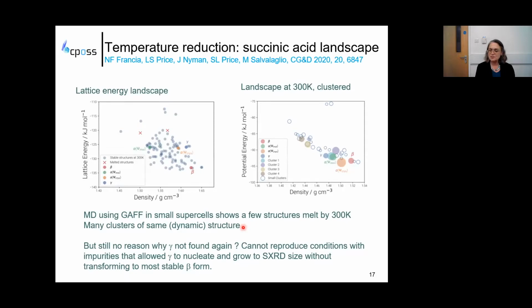And this is just showing the problem. Experimentally, they cannot reproduce the conditions, probably with the right combination of impurities that allowed this crystal to nucleate and grow to a size that the student was able to pick out of the mess alongside it. And it had grown to this size without transforming to the most stable beta form. So actually what's going on in your crystallization is a kinetic competition between nucleation, growth, and transformation in size, which aren't in our theory calculations at all.